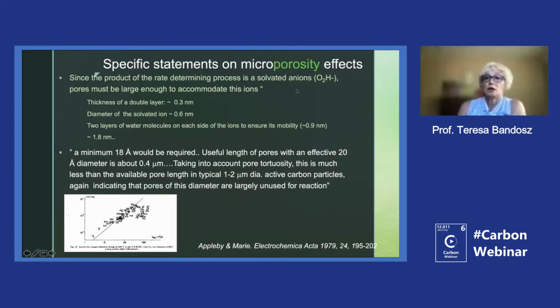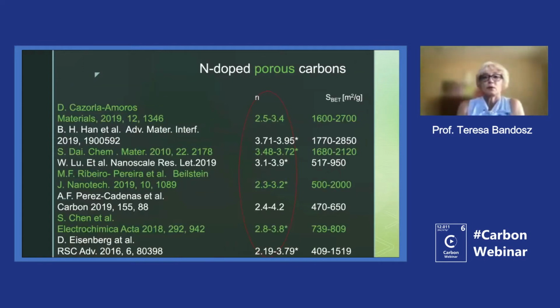So if we assume that HO2 minus ions enter the pores, they have to be solvated, and there is also the thickness of the layer and so on. So the pores should be larger than 18 angstroms in diameter. But then of course, recently a lot of papers have been published on the ORR and doped carbons,